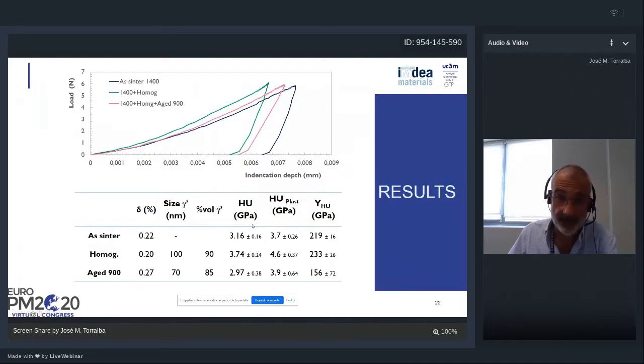Here we have a summary of results for the material sintered at 1400. Later we will compare with the 1250 degrees sintered materials, but here we have the three different indentation figures with the load and deformation graphs, and also here we have the calculated hardness, which is in some way proportional to the Young modulus of this material in the sintered state, after homogenization, after aging. You see here how the highest value is for the homogenized material, which was with maybe the higher level of gamma prime volume fraction and size for the gamma prime precipitates.